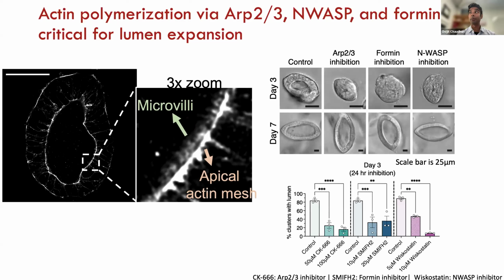We then inhibited actin polymerization using inhibitors of the ARP2/3 complex and N-WASP, which mediate formation of a growing dendritic actin network, as well as formins, which are involved in growth of a more bundled actin network. And what we see is that inhibition of any of these components potently reduces and inhibits the formation of clusters with a lumen, suggesting a role of actin polymerization in luminogenesis. And this was really the only class of inhibitors that did inhibit luminogenesis.